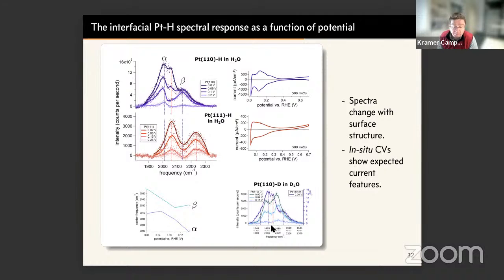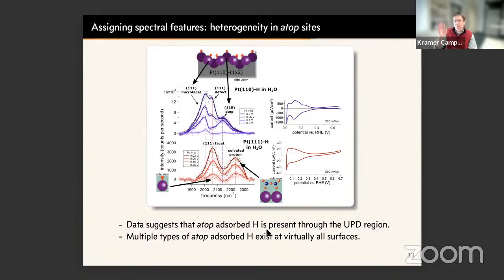spectral features are shifted by a factor of 1.41 or so, as you would expect, and are also frequency dependent. Now, of course, the absorption cross sections of this, the spectrum don't look the same, but this is perhaps sensible or at least understandable because the absorption cross-section of this deuterated species need not be the same as the hydrogenated one. So I do not have time to get into these details.